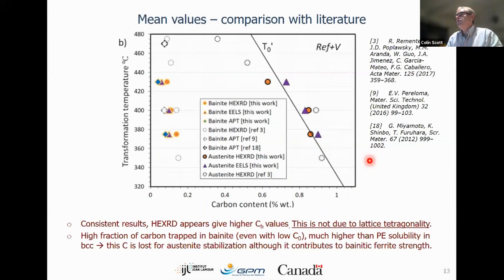So we compared our values that we found with what's available in the literature. There isn't very much for low carbon bainite. There's a lot of data on high carbon bainite because it's a lot easier to work with. But on lower carbon bainite like this, it's not so easy to find. But we did find 3, and we've compared our values here. The colored points here are our data from the 3 different techniques that we used, and the open points are from the literature. So it's consistent. We don't find a huge difference.